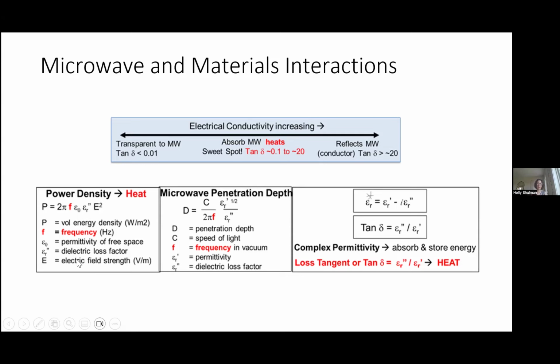Also want to point out that power density is proportional to frequency. So you go to higher frequency and you're generating better power density. But on the other hand, your penetration depth is inversely proportional. So you want to get some sort of depth so that you can get a lot of volume heated. And 2.45 gigahertz is kind of a compromise frequency. Everything is a compromise in engineering.